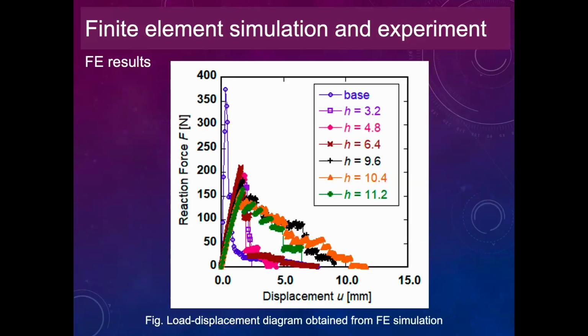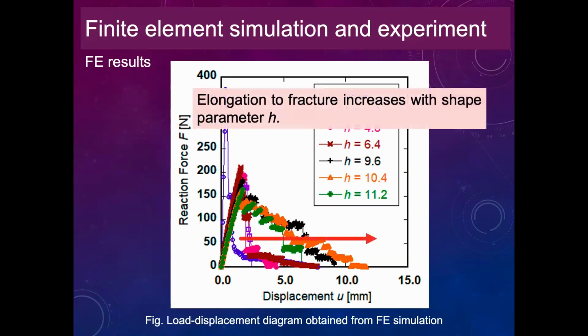This is the result for the load displacement curve obtained from the FEM simulation. First of all, we look at the base metal data, which is shown as a blue line. In the blue line case, the load increases linearly with increasing displacement. After reaching the maximum load, the load dropped sharply as shown here. So from this result, the base metal shows brittle behavior during the fracture process. For the other cases of the H parameter, it was found that the elongation to fracture increases with the shape parameter H.